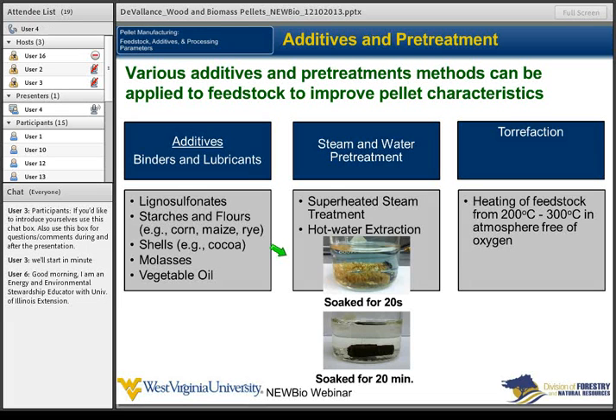And here's just some examples of some studies we've done. We did some hot water extraction at various levels, but these two pellets were the same raw materials. This was hot water extracted at 170 degrees for 45 minutes prior to making pellets, and this one was just raw wood particles pelletized. And you can see after soaking these pellets for 20 seconds, they've pretty much come apart. When we use a hot water extraction process, we soak these for 20 minutes, and you can see the pellet here is still pretty well intact.